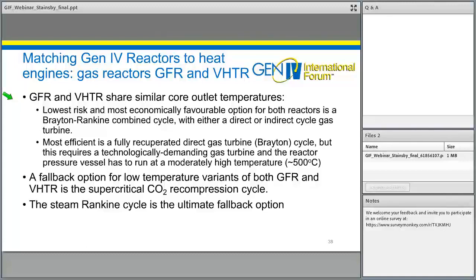And it's also quite a big turbine by gas turbine standards, because that single turbine has to create all of the power from the reactor rather than just the high temperature fraction of it. The fallback option for low temperature variants of both GFR and VHTR is the supercritical CO2 recompression cycle. And ultimately, for all of these plants, the steam Rankine cycle is the ultimate fallback option. If you look at HTR-PM in China at the moment, HTR-PM is a high temperature gas pebble bed reactor, but that's aiming to drive a gas turbine steam cycle, with things like the Brayton cycle being a future option.